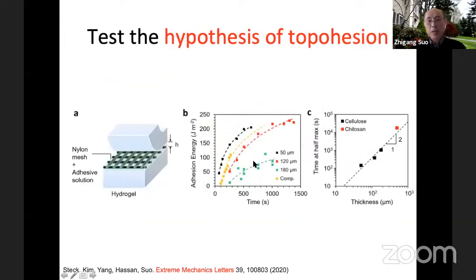So that's the hypothesis. We actually did an experiment: we controlled the thickness of the adhesive by using a nylon mesh. We can buy nylon mesh of different thickness—50 micron, 120 micron, 180 micron—and then measure adhesion energy as a function of time. You can see for thinner adhesive, the same adhesive, you reach a steady state faster, no problem. Furthermore, the time to adhesion really scales with thickness by this diffusion time scale—it scales with thickness squared, h squared. There's no mystery; it's the diffusion of little ions that causes the problem.